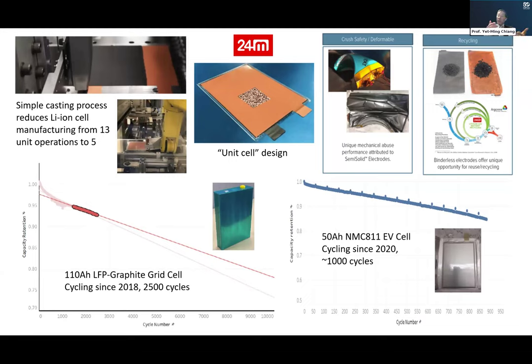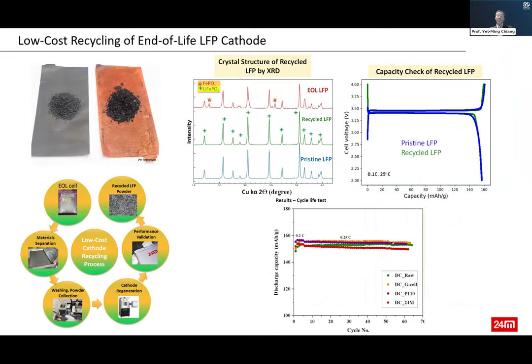And so there are interesting characteristics. You see a picture in the upper right here of extreme deformation, which is possible without causing a fire or even a short circuit within the cell. And that's because it's a softer electrode, right? It's a thicker, softer electrode. But let me talk a little bit about the recycling of these, which is the far right here, right? Okay, so this goes directly towards the point that Professor Abbott was making. Let's avoid shredding. Right? The so-called unit cells at the end of life can be unzipped, almost like a Ziploc bag. Okay? And the cathode and anode both can be removed, as you see in the upper left-hand corner here, just by simple mechanical scraping, because there actually is no binder in there. It's a binder-free system. Okay?